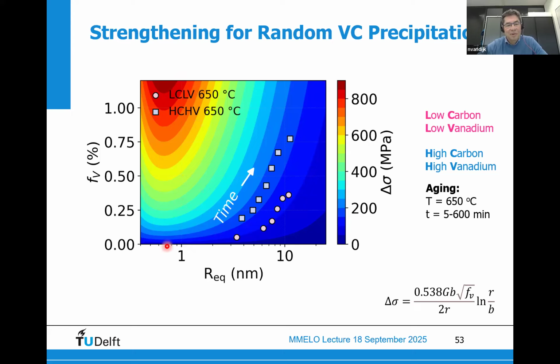And you see that for the contours that we follow in this particular experiment, we nearly follow a constant value. And that explains why we have this plateau in the strengthening. And only if we would reach values that are close to the equilibrium with a further coarsening, you will have a continuous reduction at later times.